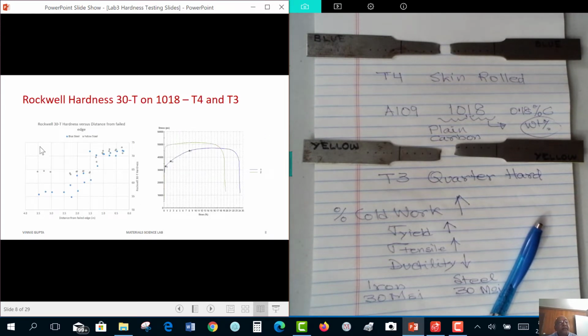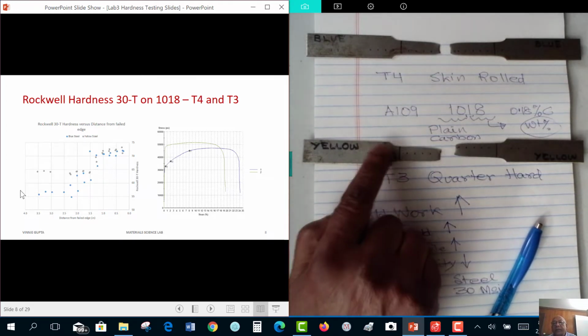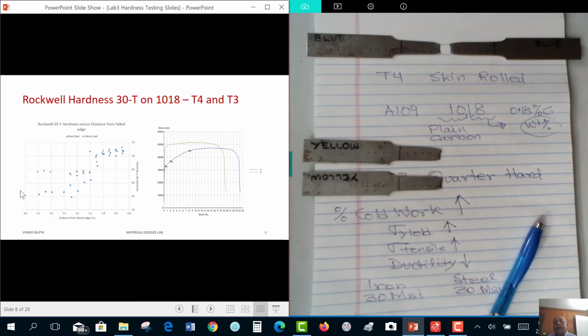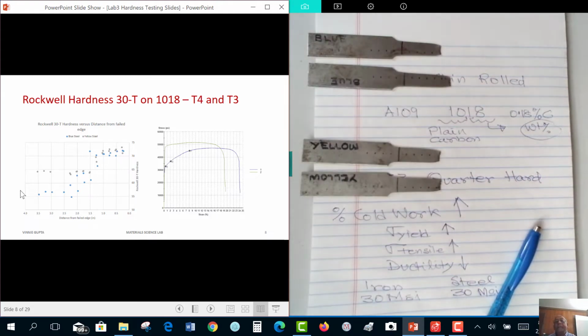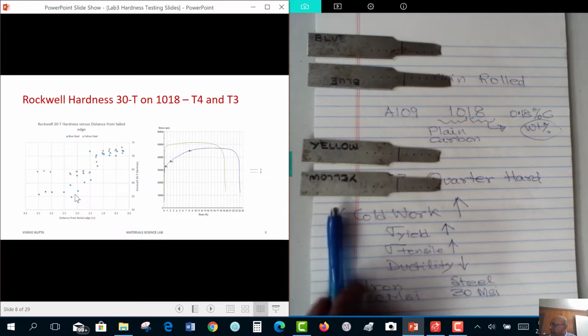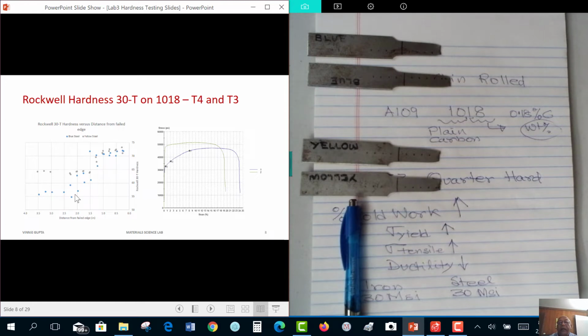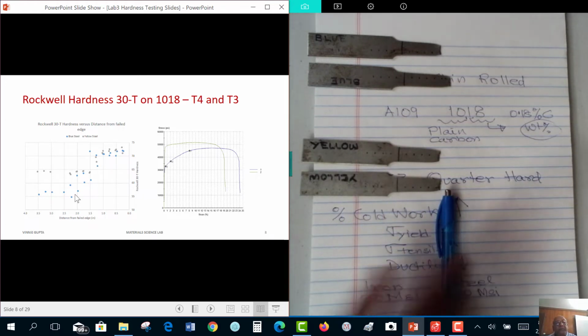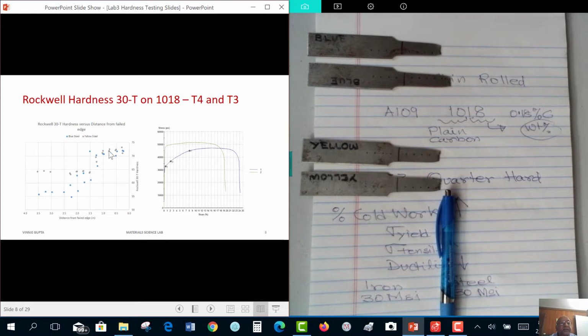Okay, the second part of the lab was I'd given you the Rockwell hardness 30T values along those tensile specimens, along these specimens where you see the dots. And basically what you did was you took the half lengths and then you plotted from left to right. So when you plot it left to right, first of all, you see that hardness is constant. It is constant in this grip area. And then as you start to deform, hardness begins to increase.